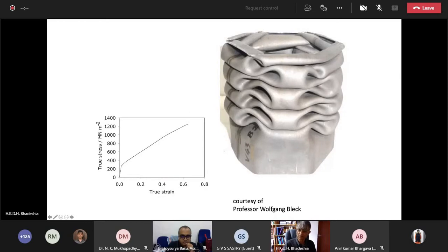And this is an example of a TWIP steel which has been tested in the same sort of scenario that I showed in the movie. Now, there is a problem here which Wolfgang Bleck identified, and that is that the TWIP steel only absorbs sufficient energy after a large amount of strain. And a large amount of strain only happens in the most bent regions here.